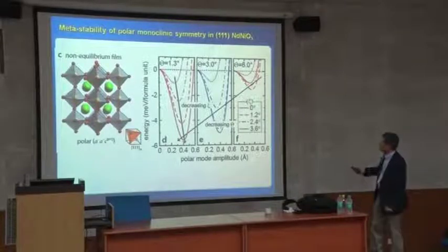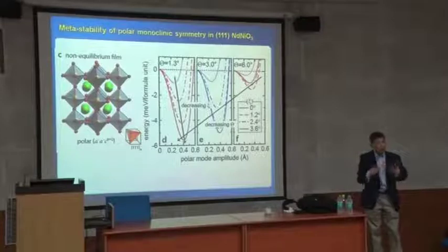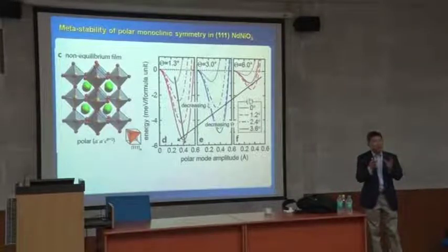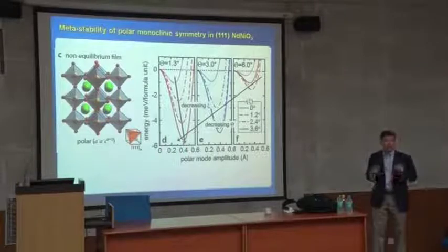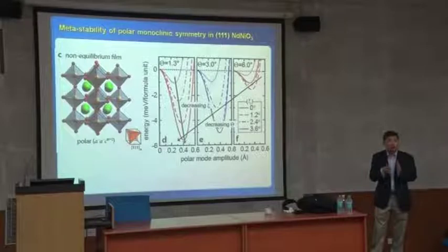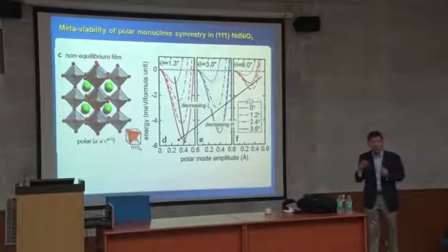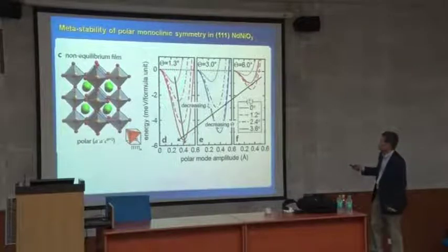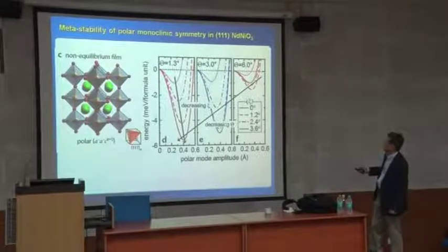So in order to do that, we actually calculate. You provide the structure information, and then there are regions, stable regions, of this material forms. And until you make the material, we don't know. But I think ideally the calculation actually tells this is true. So the calculation shows this is a very complex plot, but this is the tilting angle and rotation angle, a notation of different rotation angles, but if the rotation angle goes down to a smaller angle, you see that it is 6 degrees to 3 degrees and 1 degree, and your energy gain for the polar is more stable, and then this is the region we can go.